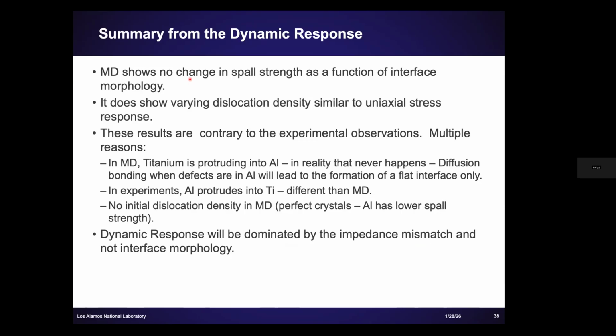I discussed multiple reasons, but I think dynamic response tends to be dominated by the impedance mismatch more than the interface morphology. I think this is important because a lot of people are doing research right now where they're trying to do interface engineering between multiple materials to control its dynamic response. What we are saying is that it's going to be the density difference between the two materials that is more important than changing the morphology. This also gives us the freedom, if we have to join materials that are going to be used in dynamic applications, to use whatever technique we can to join them together, because the interface structure itself is not going to matter. It's the macroscopic difference in impedance that is going to play a role in dictating the overall response. Okay, so with that, I'm almost out of time, but hopefully we can do questions still.